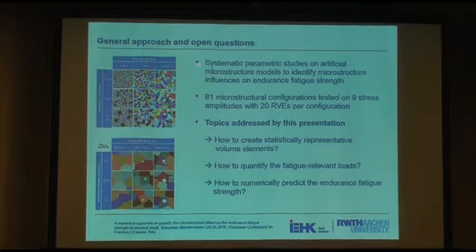So we have performed a systematic parametric study on artificial microstructure models in order to identify these microstructural influences on the endurance fatigue strength. We have investigated 81 different microstructural configurations, which were tested on 9 different stress amplitudes. For every configuration, 20 statistically representative volume elements, or microstructure models, is the better word, were used.